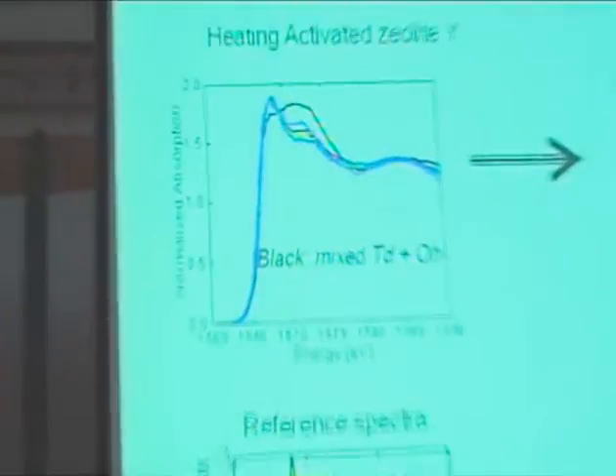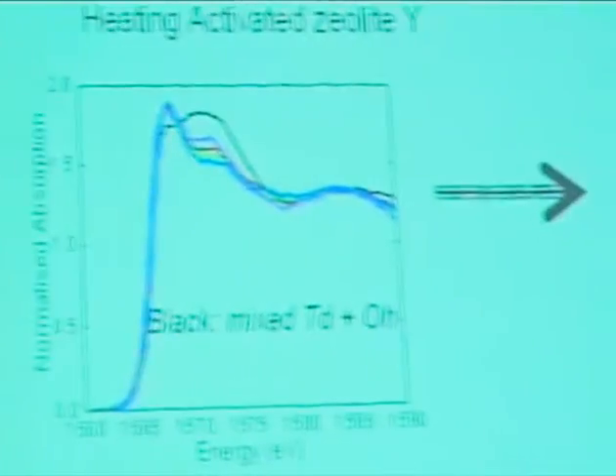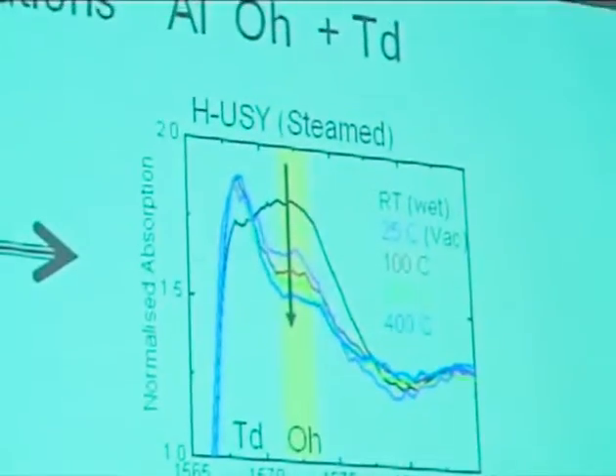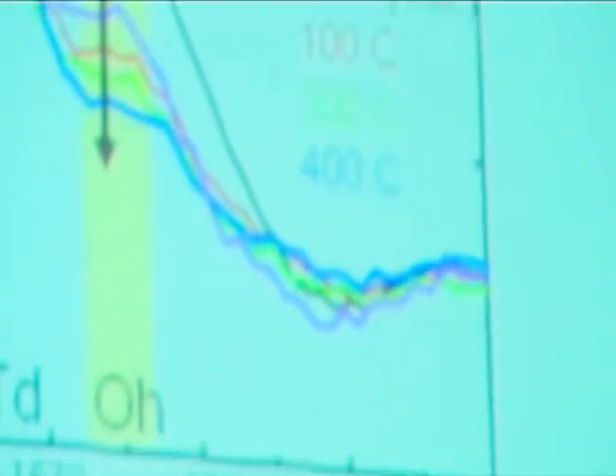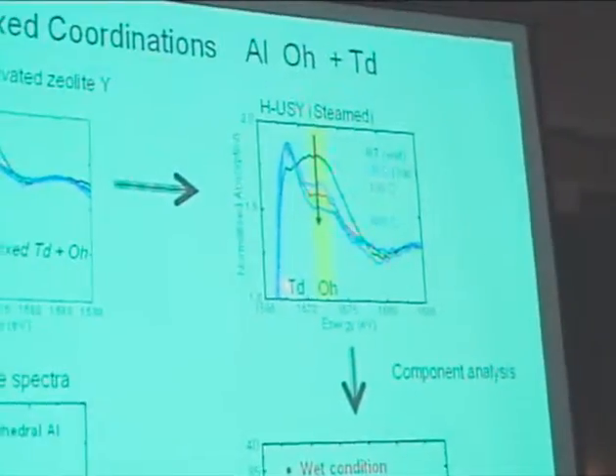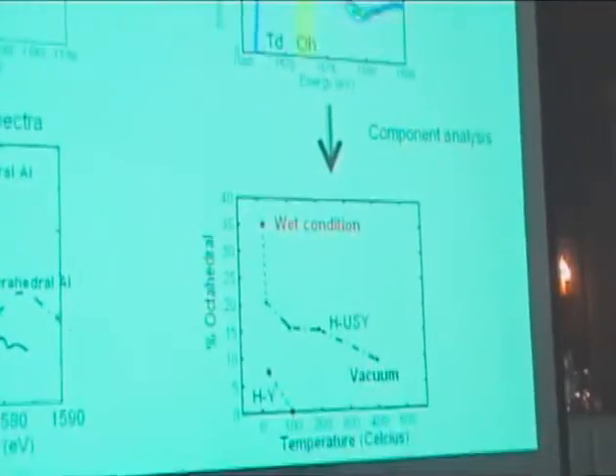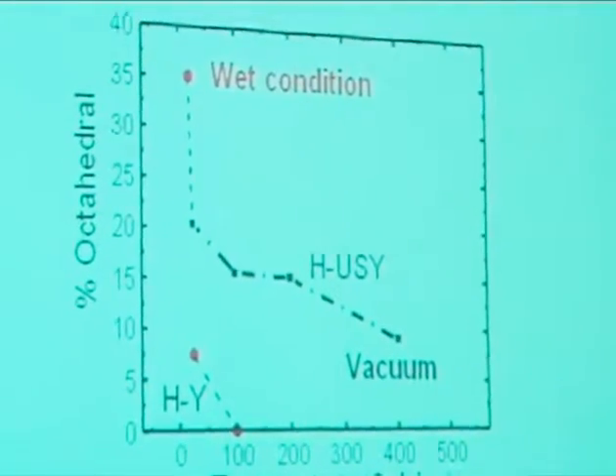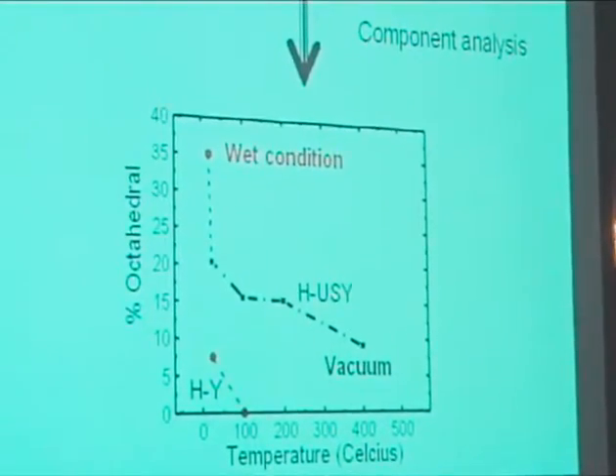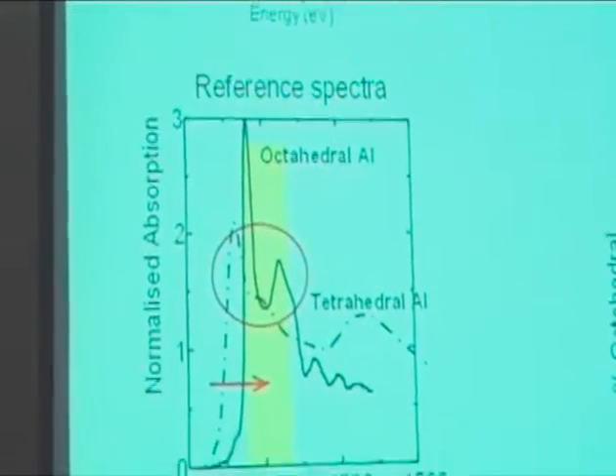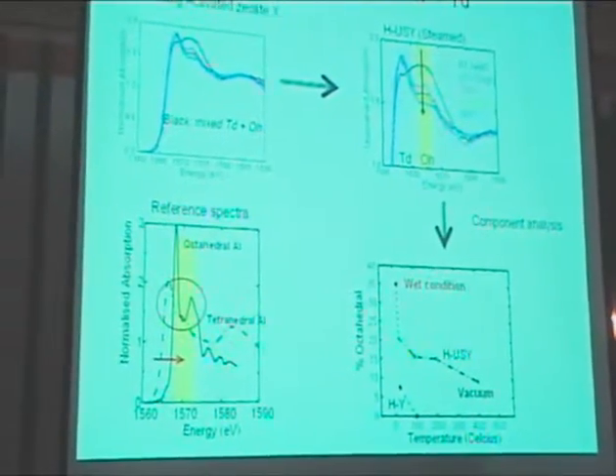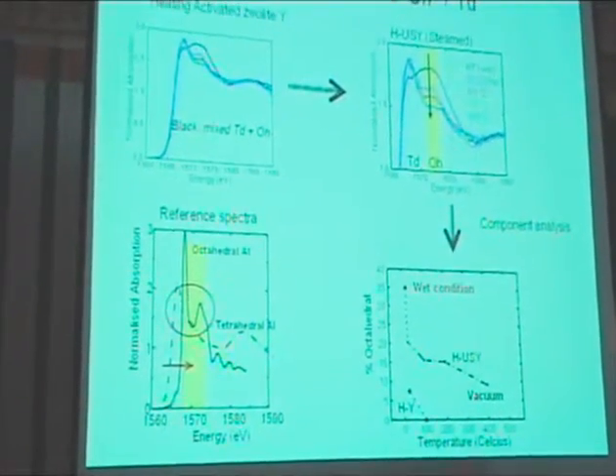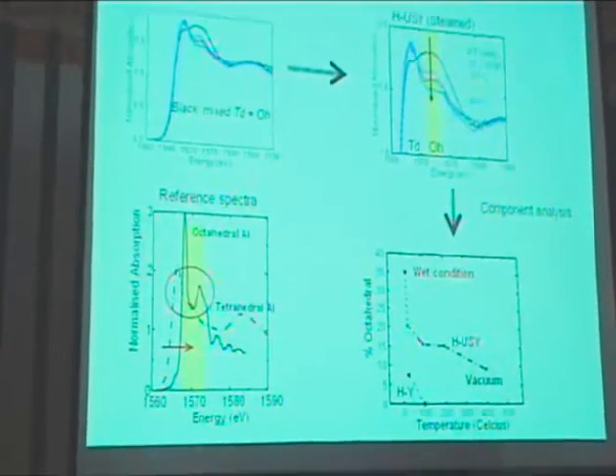And you can do studies like here. The octahedral by heat treatment can be brought back. So we have shown by this method that not all octahedral is extra framework. We have several publications, NMR and EXAFS, or XANES, that show that quite a bit of the octahedral can be brought back to a tetrahedral position. So our opinion is that this octahedral aluminium is still hanging on the lattice. It just has taken up a few waters, and it has gone from tetrahedral to octahedral, but when you remove the water by heating, drying, then you go tetrahedral again. Of course, there is still also some octahedral, which is the so-called extra framework aluminium. But that's not the 100% story.